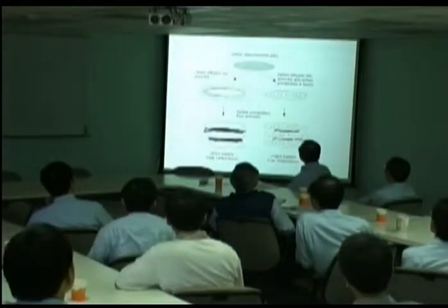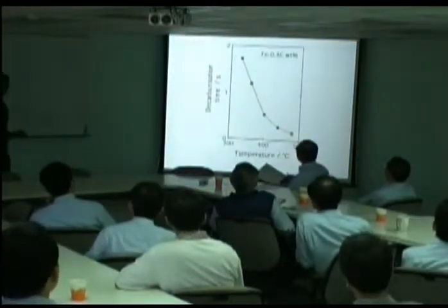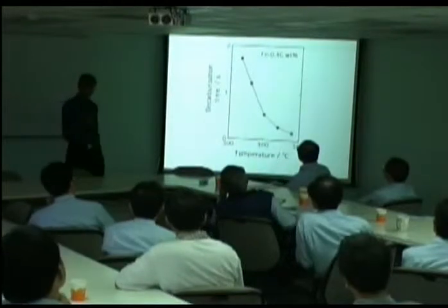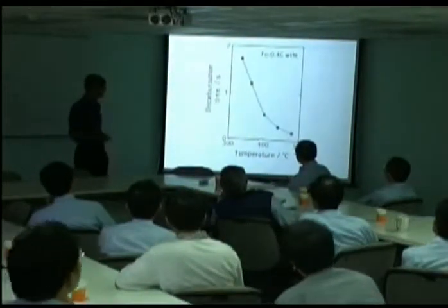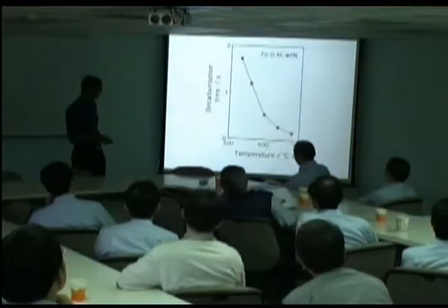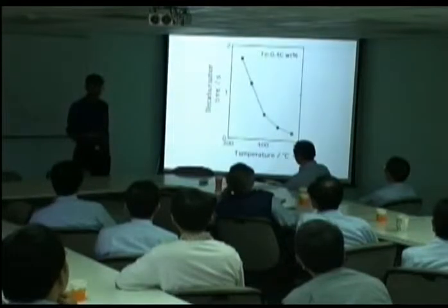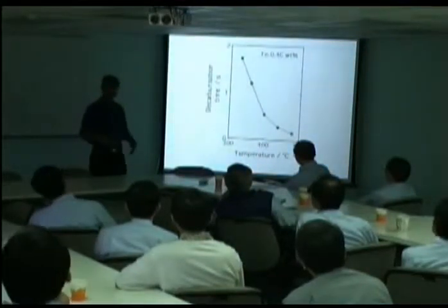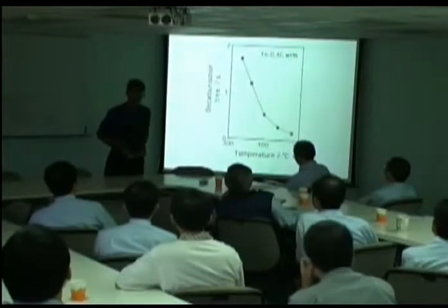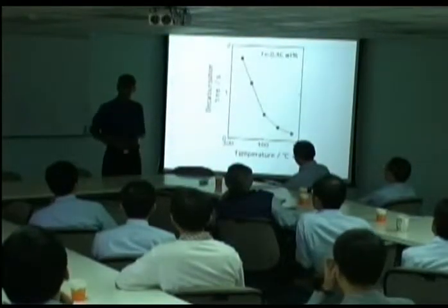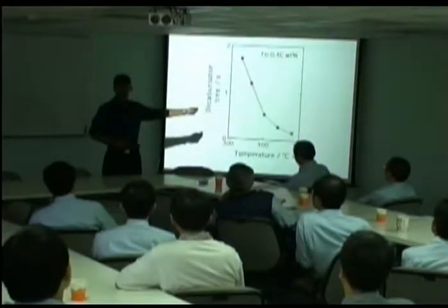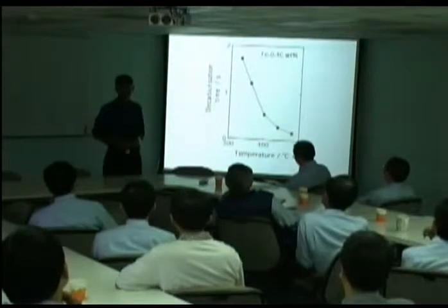Let's investigate how much time it takes for this carbon to escape. Well, here is a calculation of the time required to decarburize a plate of bainite as a function of temperature, and you can see that it's a fraction of a second. So by the time you do the experiment, it will have changed. So there is no experiment you can do in which you can find the carbon inside the plate, even if it was there at the beginning.